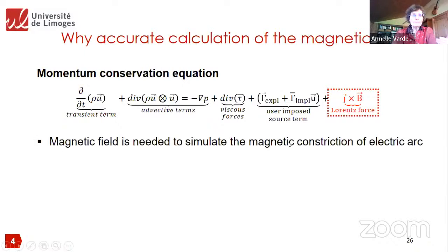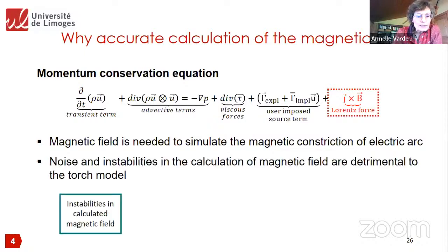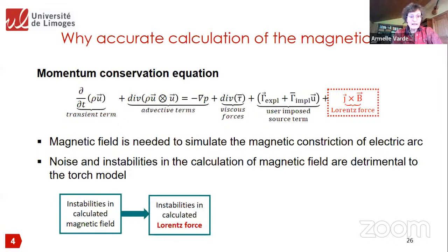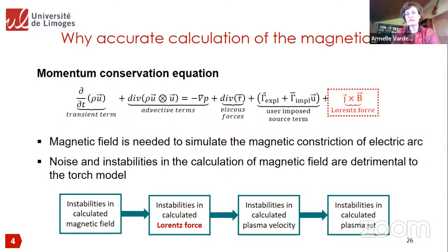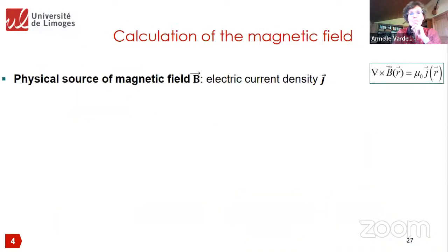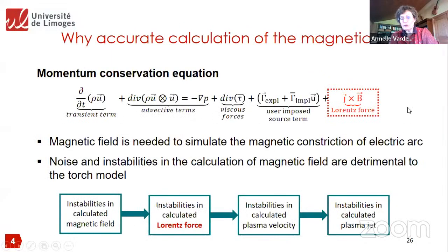And also, we need an accurate prediction of the magnetic field to simulate the magnetic constriction of the electric arc. In fact, if you have some instabilities in the calculation of the magnetic field, you will have some instabilities in the calculation of the Lorentz force, so also in the plasma velocity and in the plasma jet. Okay. Now, when you look at the real world, you have the magnetic field, and the source of the magnetic field is the circulation of the current, so the electric current density. Okay, and they are linked by the equation you can see here.